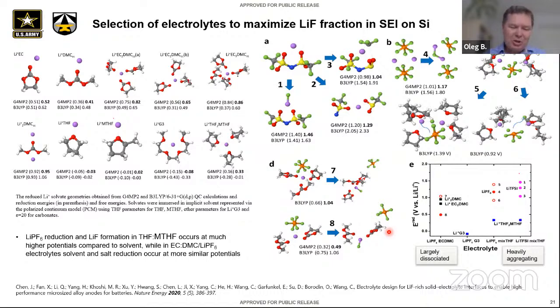It's only initial stages, but if solvent and PF6 are well separated, it's the majority component, so it's easier to predict. When there is a soup of things, it's very tough. One of the tough things for me, for example, is when I took lithium ethylene dicarbonate and put it in solution as it forms. I do see initial aggregation, but even if I run hundreds of nanoseconds, the final solvent never goes out.